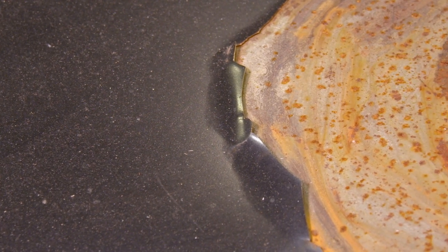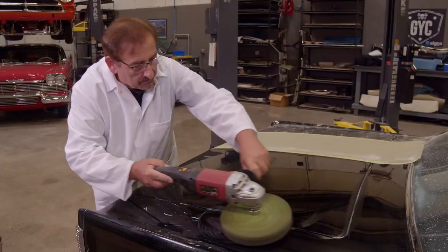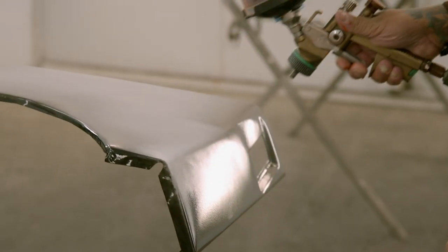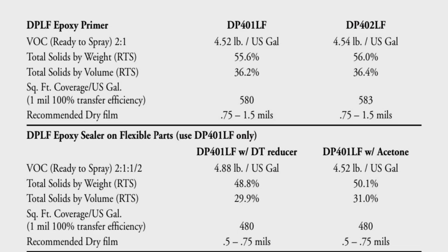Metal has to be sealed with an epoxy — in our case DP-90, a two-part epoxy designed to neutralize flash rust. The second you're done with bare metal, it already starts to rust, giving you about a day or two to get on top of it. If paint is too thin, the sun will break it down and it'll delaminate even with good substrates. You can also get too much millage and it can crack. The paint on this hood is all dull and flat. Remember the black GTX restored 13 years ago — brought in from outside and it still looked like a sheet of glass. Going forward, I'll DP-90 it first; it's a nice sealer that fills imperfections, mixed at a different ratio.